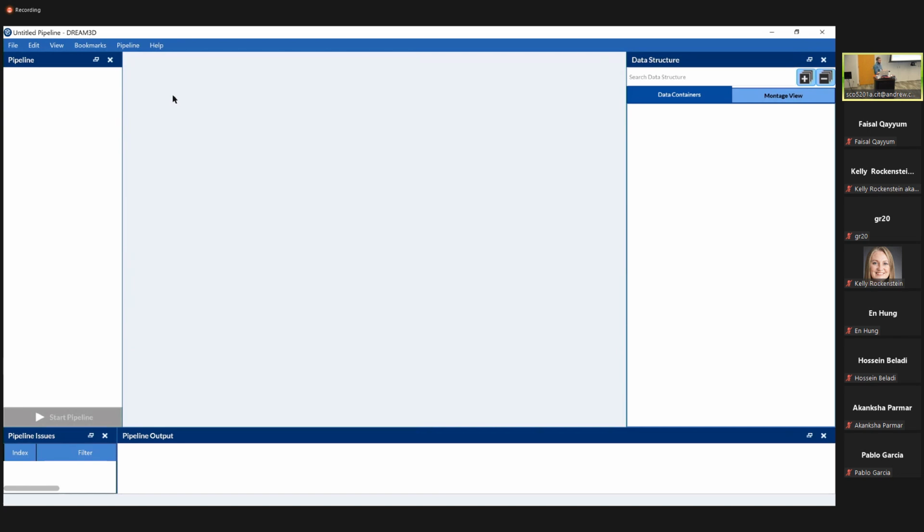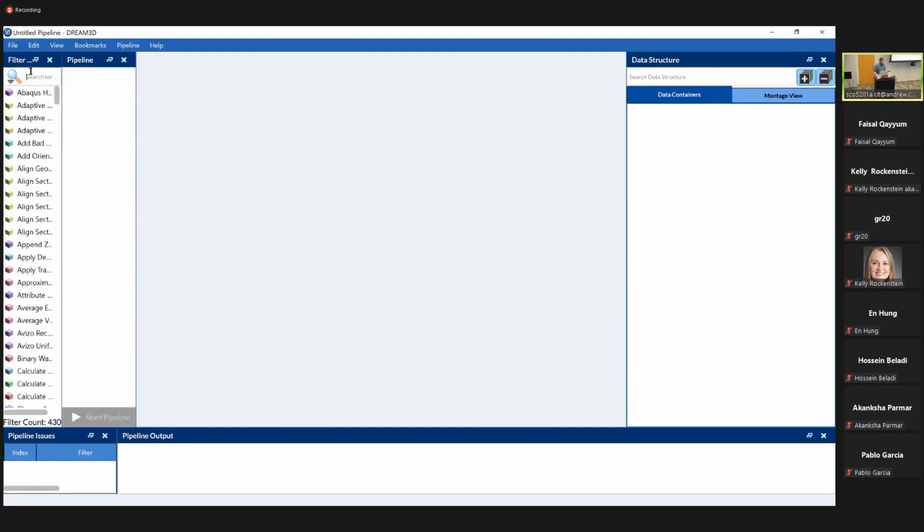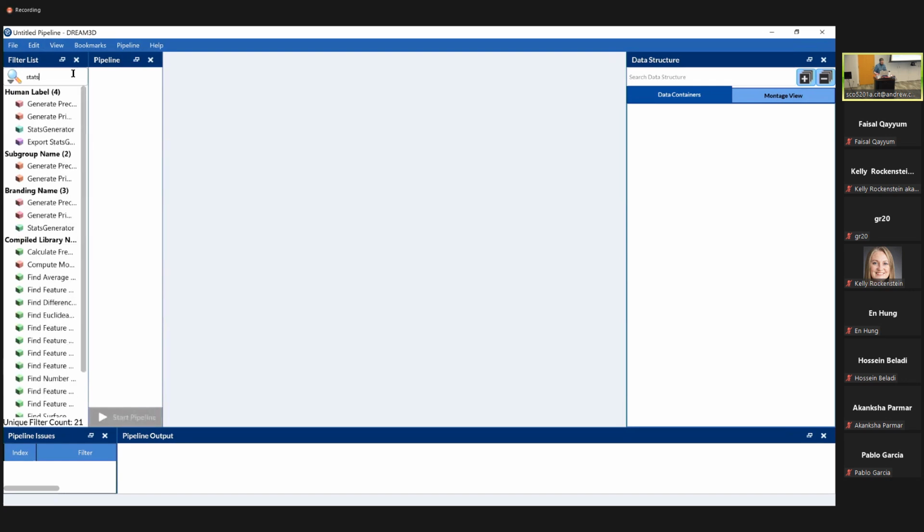So we're going to make a bimodal grain size distribution. Historically, a lot of the times when people try to do that in Dream3D, they try to force it into the single primary phase, but you're never going to be able to do that because it's a log normal distribution. What makes more sense is to make two primary phases that have fundamentally very different grain size distributions. So we're going to do that right now and try to make something that's kind of like having some abnormal grains in the structure. So I'm back in Dream3D. I need to get Stats Generator because I opened up the window. Whoops.